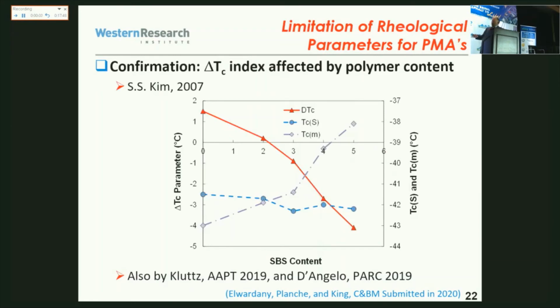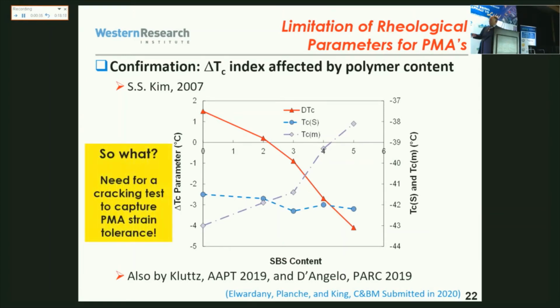Okay, so we did more data mining, just to confirm what we already saw: when you start with a base asphalt and you add polymer to it, in almost every case you will get a lower delta TC. That means delta TC is not giving the proper ranking for polymer modified asphalt, because 5% polymer is supposed to work better than 1%, and we are saying just the opposite. So there is something wrong here. We need something else. We need to be able to capture the polymer modified asphalt strain tolerance.